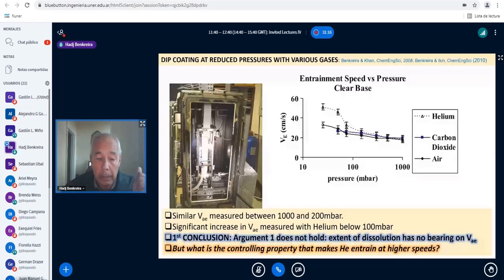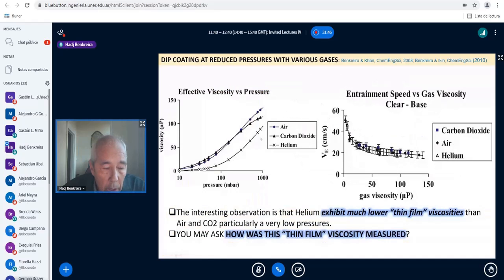And then you ask yourself, why is it that helium, compared to CO2 and compared to air, displays much higher dynamic gas entrainment velocities? Why is this? That was our next set of experiments and the theory that we developed. What we observed, when we plotted the viscosity of these three gases against pressure, is that the viscosity of air and the viscosity of CO2 are pretty much the same, but the viscosity of helium is quite different, much, much lower, particularly at very low pressures.